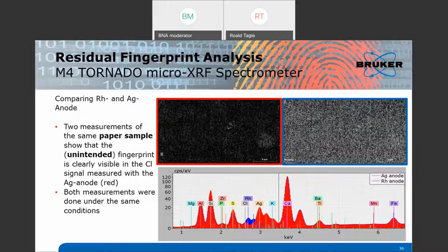or elemental distribution of the same area, now that you know where to look, you have the feeling that you can see some lines there, but if you did not have the left one to guide you, it's very difficult to get a significant contrast to identify the fingerprint in the second one. So basically, the silver anode really helps a lot to identify the chlorine and get a good contrast for this element on a sample.